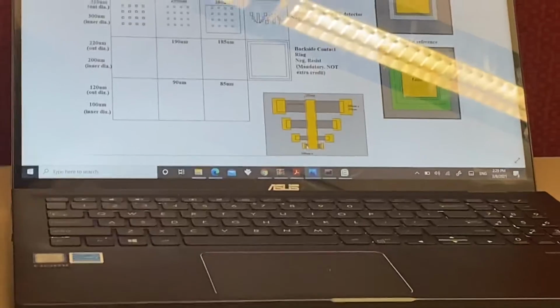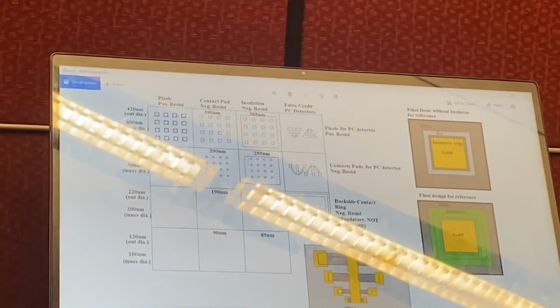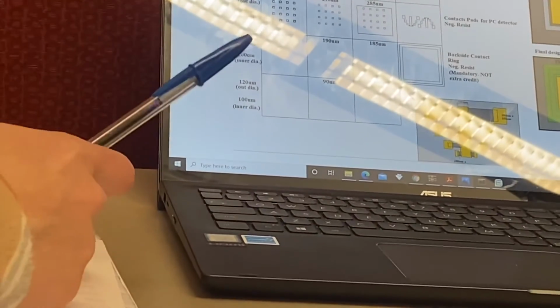Referring to that one specifically, I meant the pad, I'm sorry. That's the minimum dimension a gold pad needs to be. So for example, on the smallest one, even though this smallest area may only be 100 nanometers by 100 nanometers, this gold pad needs to be at least 150 by 150. But yeah, when they get bigger, you just need to make them big enough to cover the full thing here, right? But it doesn't need to be much bigger.